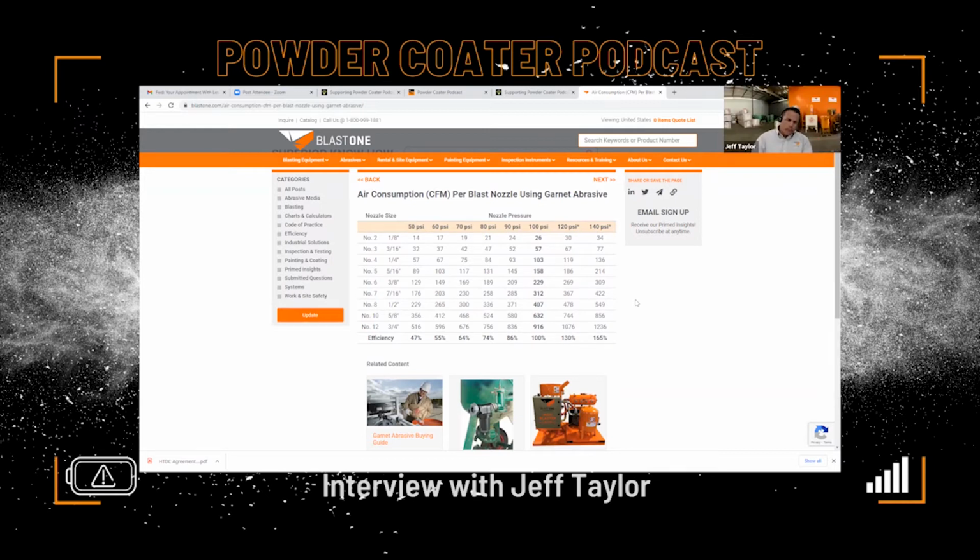So we can talk about blast pressure, and I know some people don't want to blast at a higher pressure for various reasons, but we can talk about the difference between blasting at 80 PSI versus 100, also 100 versus 120. And the abrasive selection that you're using does affect that as well. Depending on what type of abrasive, you may not need as high of a pressure, but the rule of thumb is 100 PSI is your start point. Anything under 100 would be a loss in production. Anything over 100 would be a gain in production.